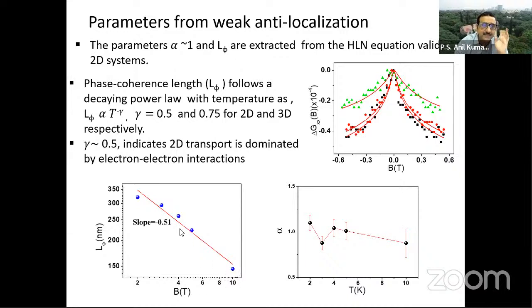Sorry, this is temperature. At different temperatures, you can fit it with this equation and extract the parameter gamma. Gamma equal to 0.5 says that it is a typical 2D system, and if gamma equals 0.75, you will see a three-dimensional system. So far, we have a crystal, and the angle-resolved photoemission spectroscopy was matching with the theoretical predictions, and the theory says it's a weak topological insulator. So we can say that it's a weak topological insulator, and it shows a kind of 2D transport in the system. That is the conclusion that we have up to this point of time.